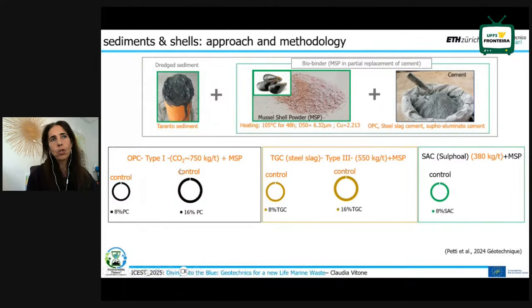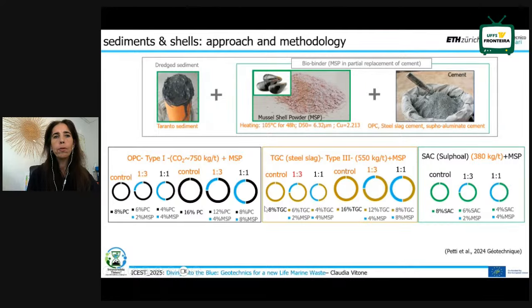So which is the rationale behind this research? What we did was compare standard mixtures, so control mixtures, obtained by mixing just the sediment with the cement, different cements: Portland, steel slag cement, and a sulfoaluminate cement. These control mixtures and their mechanical behavior have been compared with that of new, innovative mixtures, where part of the cement was replaced by this mussel shell powder, here in light blue.